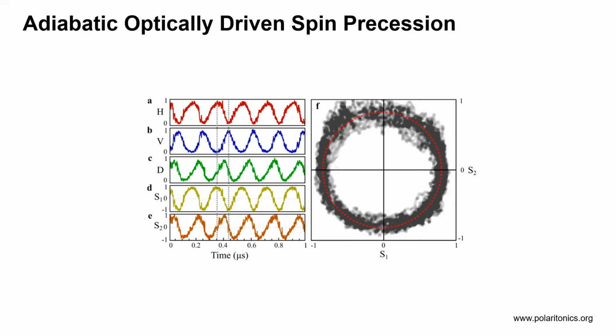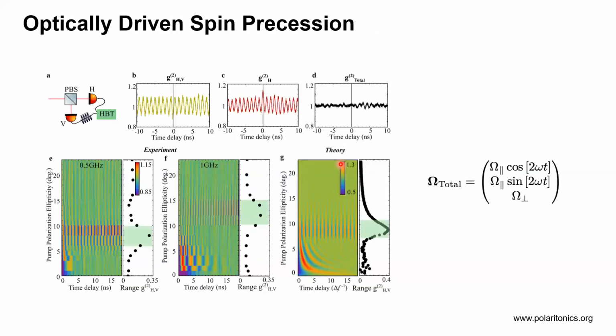Let's go now and do it fast, really fast. How fast? So fast that actually, if I look at it, I rotate it as fast as the intrinsic degrees of freedom of the splitting, of the spin splitting in the structure. And what we see here is the following. When I control the intrinsic spin splitting by injecting not an equal portion of spin up and spin down electrons, but an asymmetry there, which creates an energy splitting between the spin up and spin down polariton, and I rotate at this frequency, I hit resonance, and practically I see a spin precession that lives as long as our experiment. We have gone to microseconds.